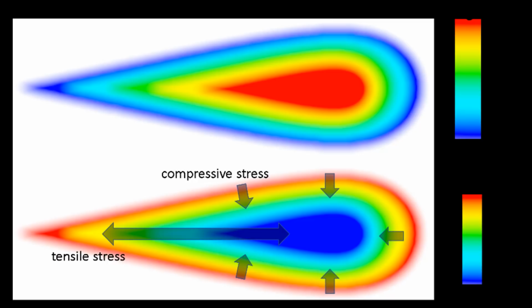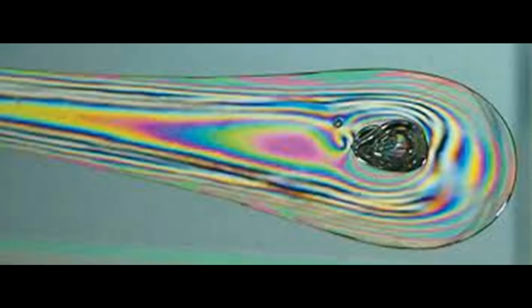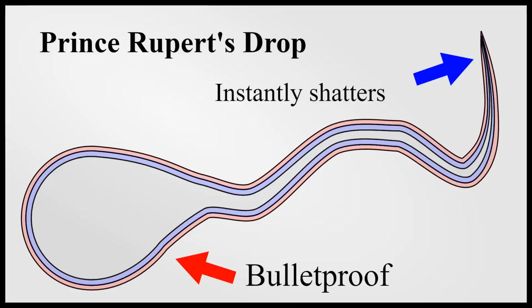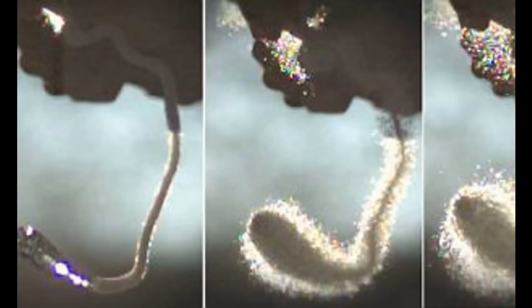shell. As the core of the glass cools and hardens, it contracts, pulling the outer shell inwards, but since the outer shell has already solidified, it remains in place, instead undergoing an internal tension force, imparting a mechanical force on the glass's crystalline structure from the inside. The result is that the teardrop head of a Prince Rupert's drop can be struck multiple times with a large hammer and will not break. However, if the tail of the drop is broken, internal stresses release explosively, causing the drop to shatter instantly.